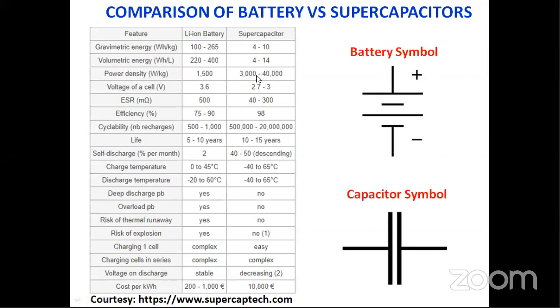And of course, the power density, as I mentioned, the supercapacitor gives a high power range. And the voltage of the cell, of course, in lithium batteries nowadays, we can have nearly 4.2 volt, or 4 volt, 4.5 volt cells. That depends on the configuration of the anode and the cathode materials. Of course, in the supercapacitor, that depends upon the electrolyte system which we use. If you're using the aqueous electrolyte system, you can limit the potential to less than 2 volt. If it is organic, you can go more than 2 volt.